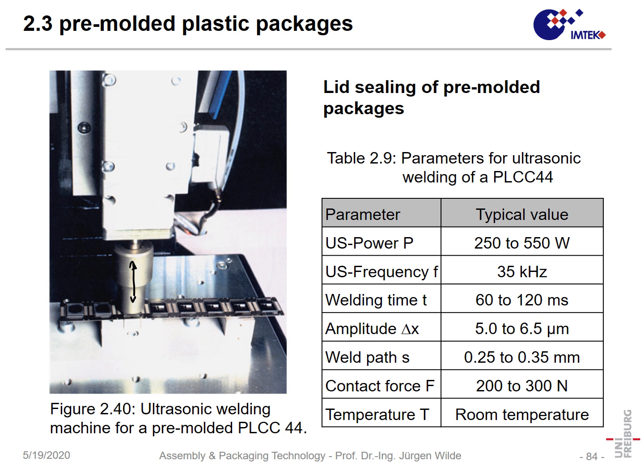We had an ultrasonic welding machine. For that machine, you put on the lid. You have a tool. That tool is moved by ultrasound. The ultrasound can have a power of 250 to 550 watt. The typical frequency is 35 kilohertz. You will not be able to hear it, but maybe you feel it because it's a very high power. And within less than 1 second, this action of the ultrasound will lead to a local melting of the package.